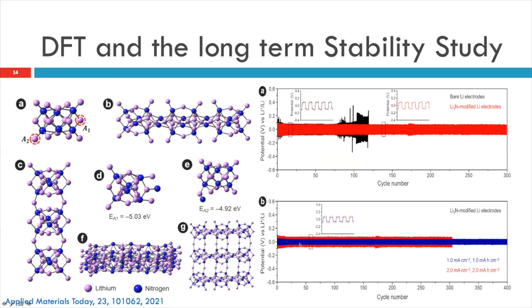And we studied some of the DFT to see how the growth is. You can see the two sites were identified, A1 and A2. One will give you horizontal growth, the other one will give you vertical growth. And when you calculate which growth is preferential, we see a very minimal difference in the energy. And we see that maybe it formed both ways, and then it created a three-dimensional film on this lithium surface. There's a very minimal energy difference in this.